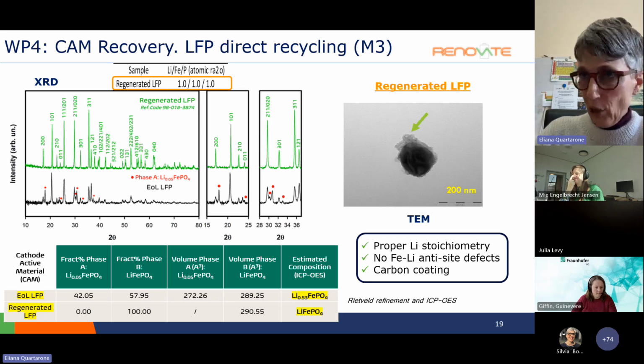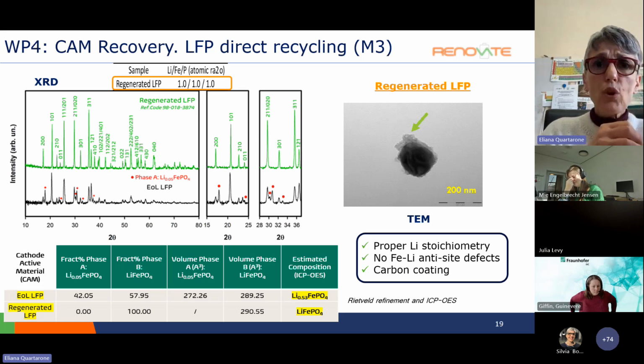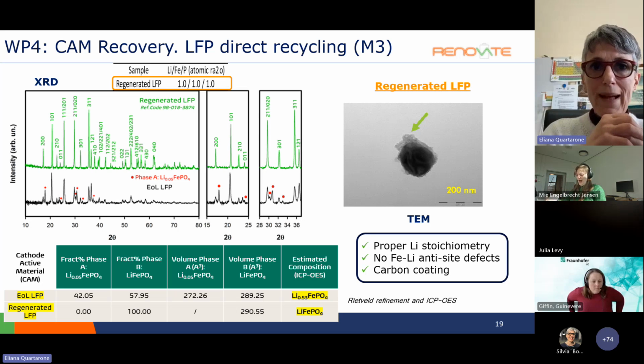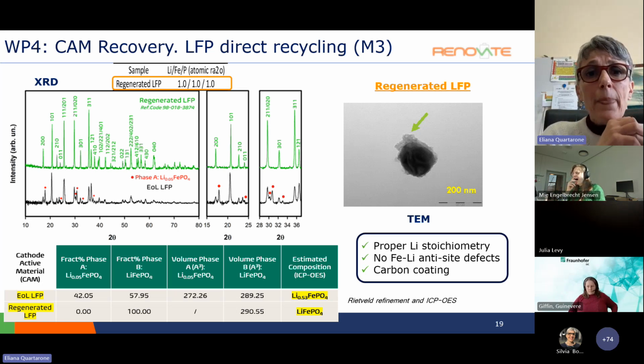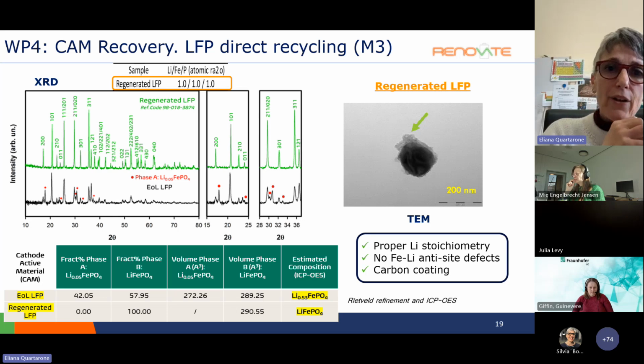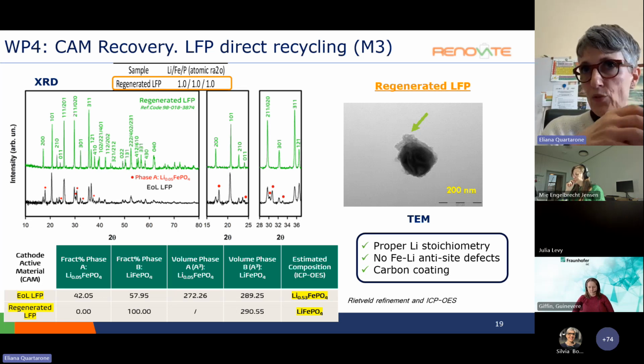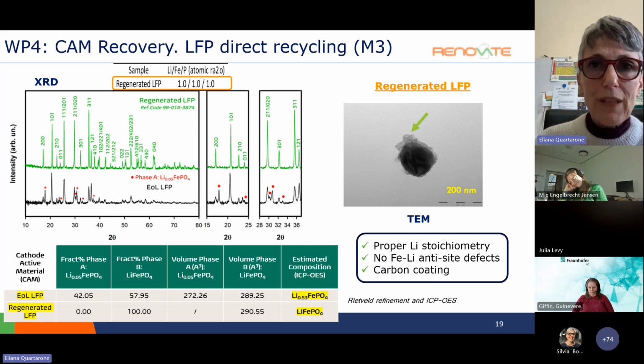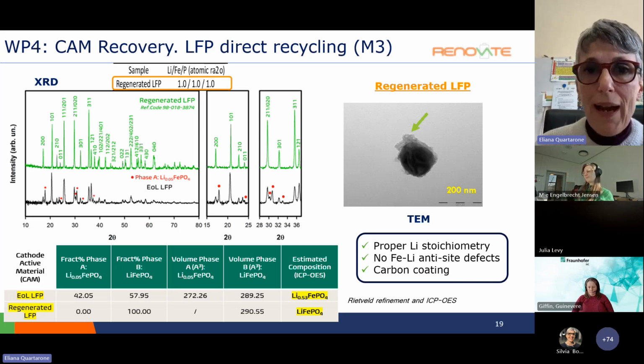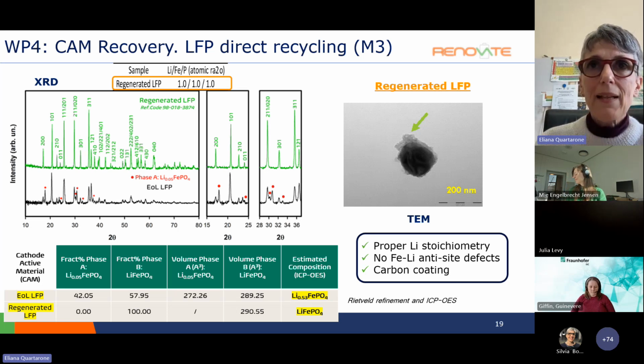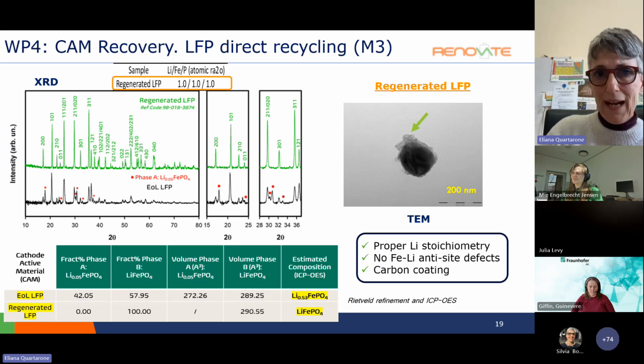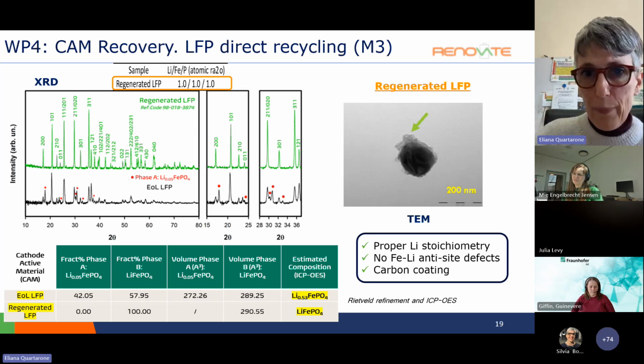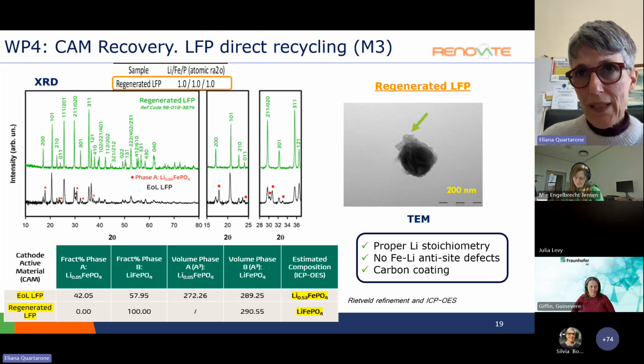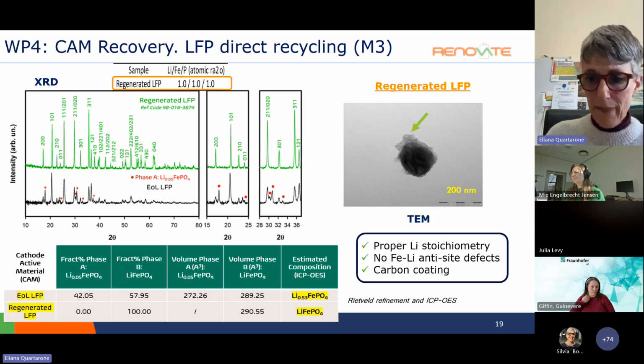We can exclude, of course, thanks to a deep structural characterization by X-ray diffractometry, the presence of any iron-lithium antisite defects that, as you know, are really detrimental to the functional performance of such cathode. But an important piece of information is that the reconditioning process we are proposing is capable of preserving the carbon coating around the LFP particles, as you can observe from this electron microscope image.